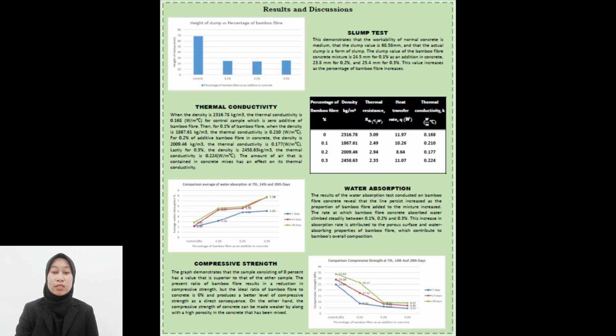And lastly is compressive strength. The graph demonstrates that the sample consisting of 0% has a value that is superior to the other samples. The presence of bamboo fiber results in a reduction in compressive strength, but the ideal ratio of bamboo fiber to concrete is 0% and produces a better level of compressive strength as a direct consequence. On the other hand, the compressive strength of concrete can be weakened by high porosity in the concrete that has been mixed.